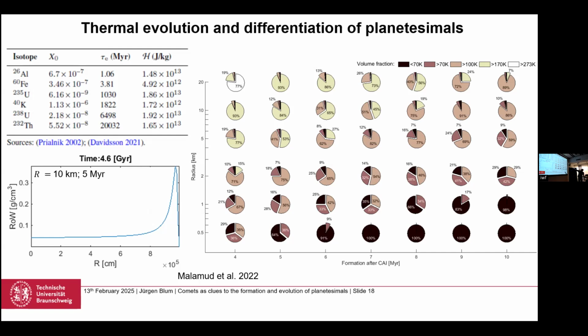And here is the map of formation time and radius. So here is a 20-kilometer radius body. Here's a 1-kilometer radius body formed after 4, 5, 6, 10 million years. And the pie chart tells you how warm they were. And of course, they're much warmer in the center than at the periphery. So those that remained cold, under 70 K, of course, are here, small bodies, because then the heat that is generated can escape to the surface, and those that form late, so not much heat generated at all. And those that form early and are large, they are the most affected. So they have reached temperatures above 273 K even. So water can not only evaporate and be transported outward, but it can also melt.